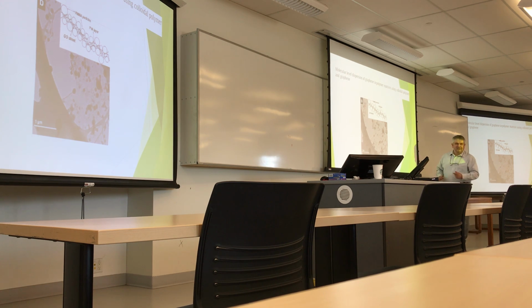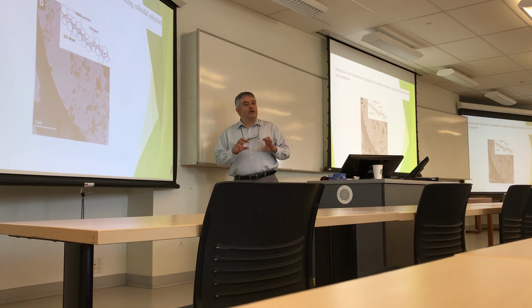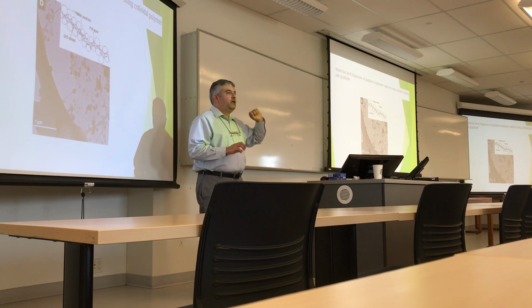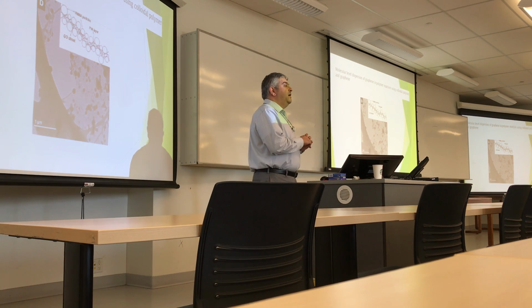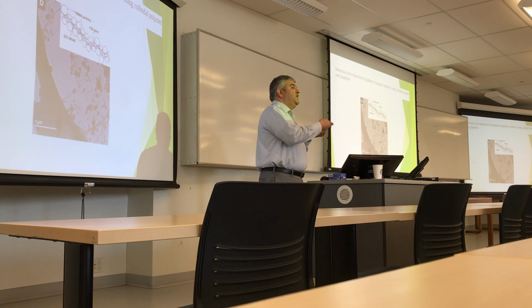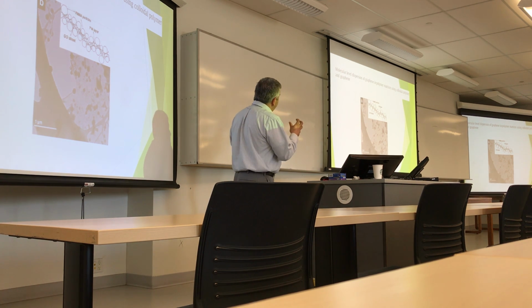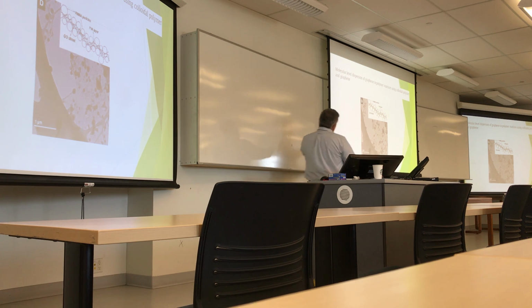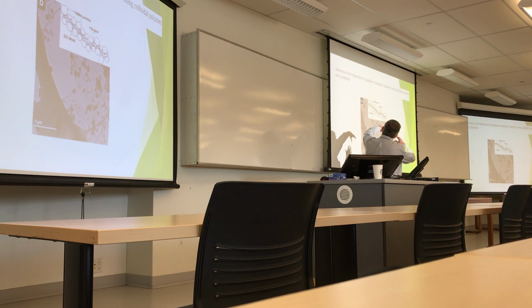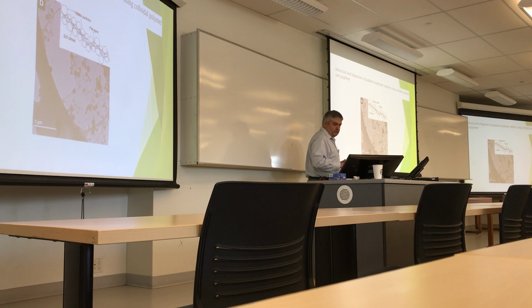So we started thinking about it. We went back to that PVA stuff that we had, and we stabilized graphene-oxide with PVA, the work that we did before. And when we put them with the PMMA, what happened was that the PVA worked as a bridge. So the PMMA started adhering to the GO using that PVA layer bridge. So it turned out that you can make films like that, and the properties were good.